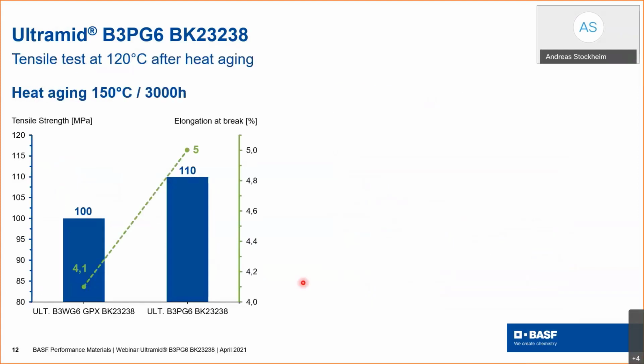In addition, we tested the B3PG6 at 120 degrees elevated temperature. The product had been heat aged at 150 degrees for 3,000 hours, and then we did an elevated temperature test. And here you can see the difference to our reference grade B3WG6 GPX in comparison to our B3PG6. There is a difference of 10% in tensile strength as well as 22% in elongation at break.